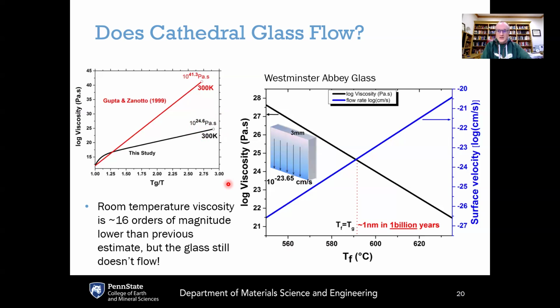So our colleague Olish Boratov did the fluid flow simulations using this viscosity. And in fact, he considered a range of different fictive temperatures, since we don't know exactly how fast or how slowly that glass was cooled, and then calculated the surface velocity of that flow. And what he found was that the glass would exhibit about a nanometer's worth of flow over a billion years. So even though this viscosity was so much lower than what had been previously thought, it's still much too high to actually observe flow of cathedral glass windows.